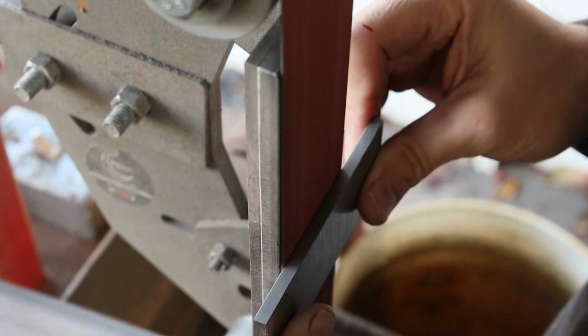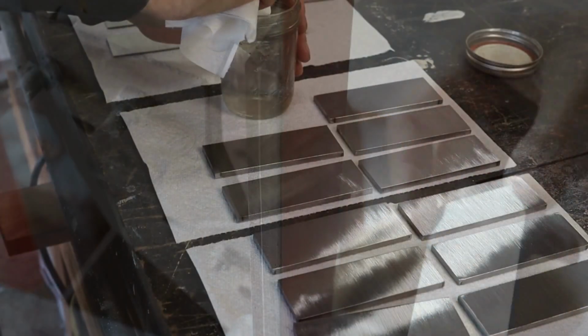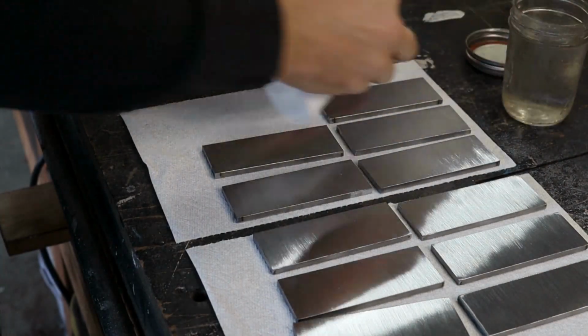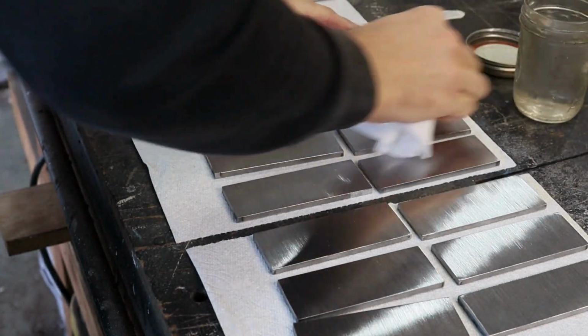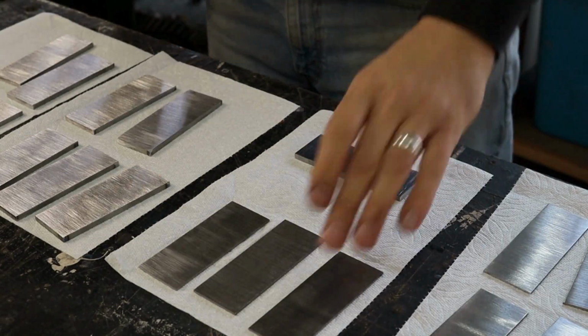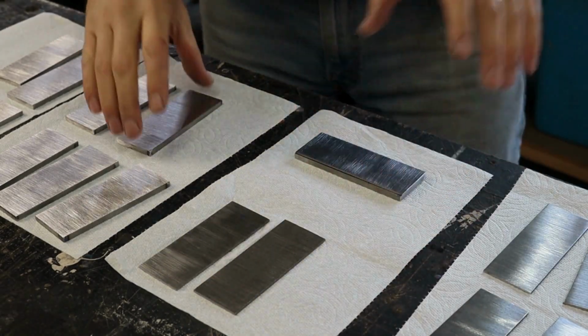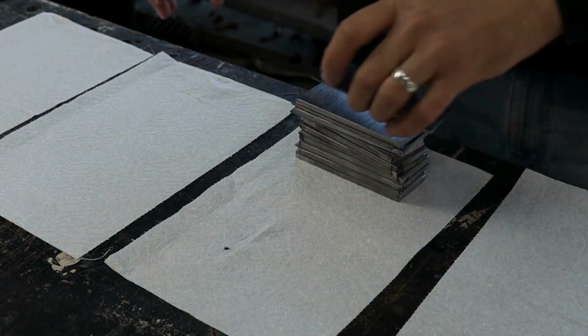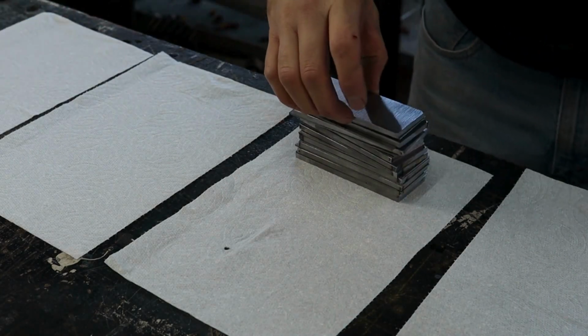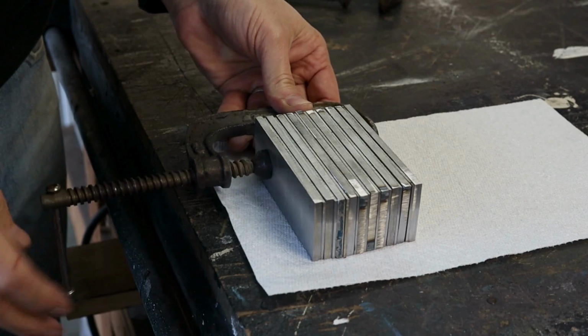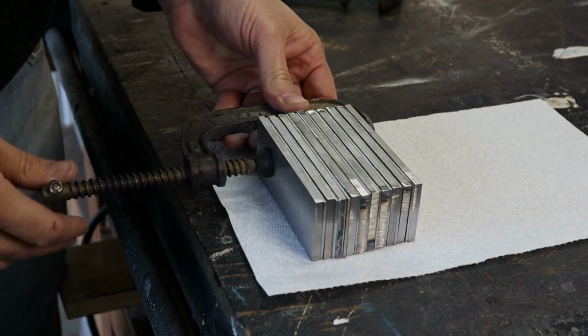We'll start with 19 layers of alternating 1084 and 15N20. This is my usual process of prepping the steel by grinding off all of the mill scale and then degreasing the surfaces with acetone. I'll stack it up and weld the corners, and then I'll give it a soak in some WD-40 before going